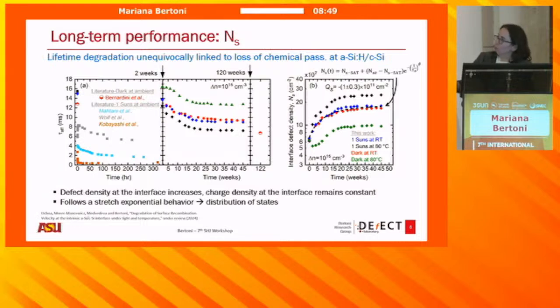And one of the things that you would notice if you take a look at this is that your defect density at the interface changes and increases as a function of time, but your charge density at the interface stays put for the intrinsic amorphous layer. The doped amorphous layer has a change in QS, but I have limited time. I'm happy to chat about the doped layers later.